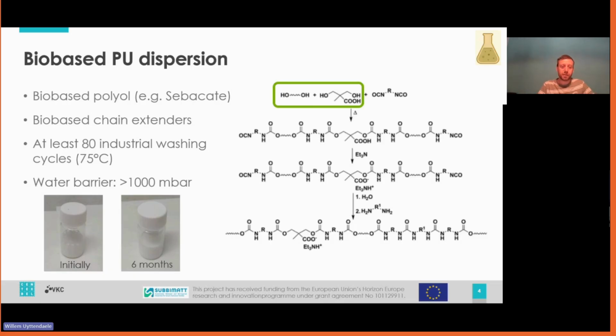We combine this also with bio-based chain extenders to, in the end, get to polyurethane dispersion in water with a high bio-based content. Of course, here this material is not fully bio-based because we still are working with isocyanates which are not available as fully bio-based materials. The work we did here at Textiles is mainly on improving what is possible with these bio-based polyurethane dispersions and especially improving their washability. So in the end, with these bio-based polyurethanes, we could get to 80 industrial washing cycles, which means that they get washed at 75 degrees 80 times in a row.